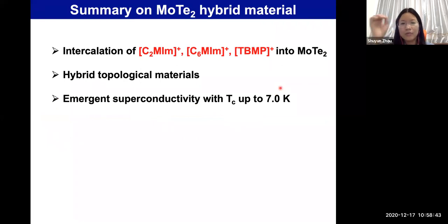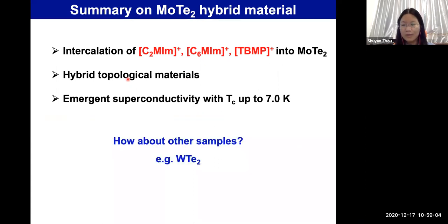So I have shown you that by intercalating these different organic cations into molybdenum ditelluride, we can obtain these hybrid topological materials, and we can induce superconductivity with TC up to 7 Kelvin. So how about other samples? One thing that I would like to try is tungsten ditelluride. It overall has very similar properties to molybdenum ditelluride, but with some small difference in that the monolayer flake shows this quantum spin Hall effect.